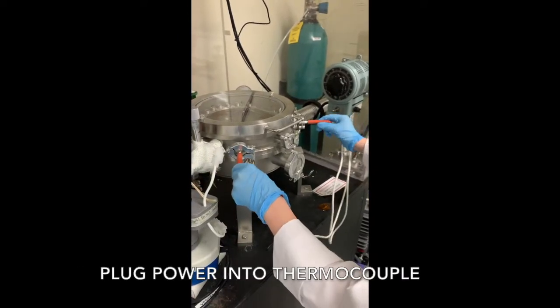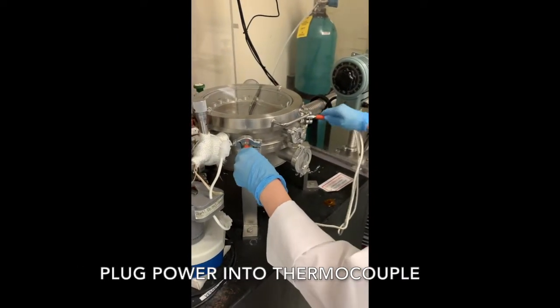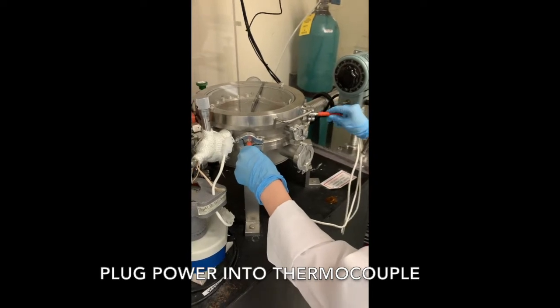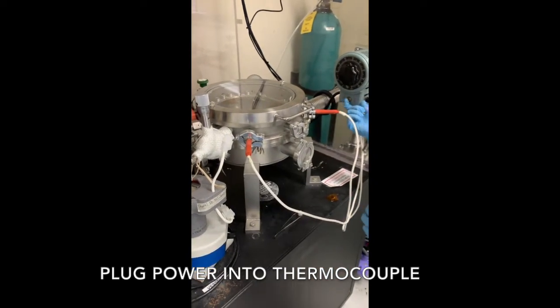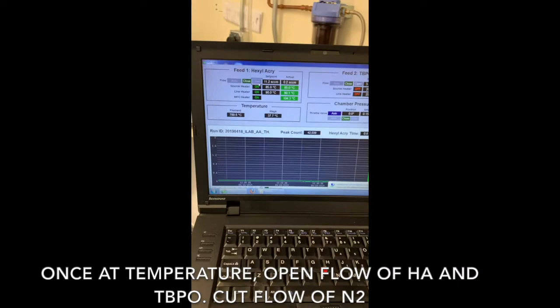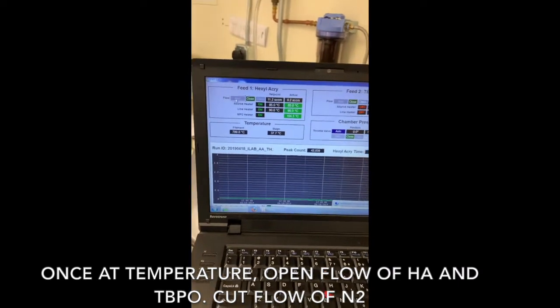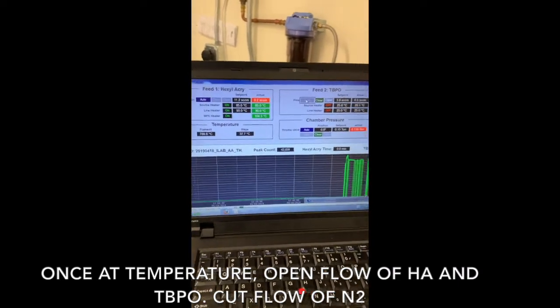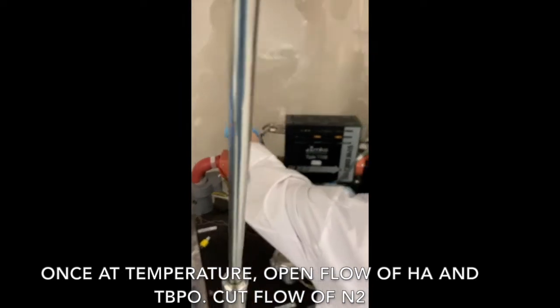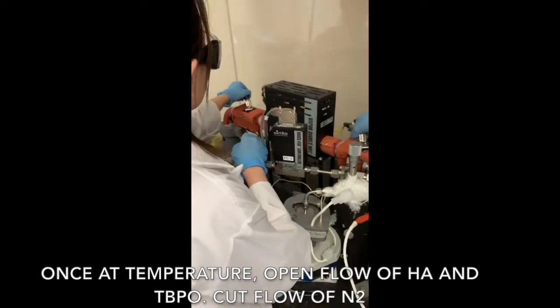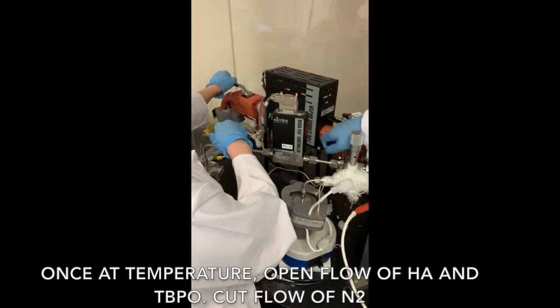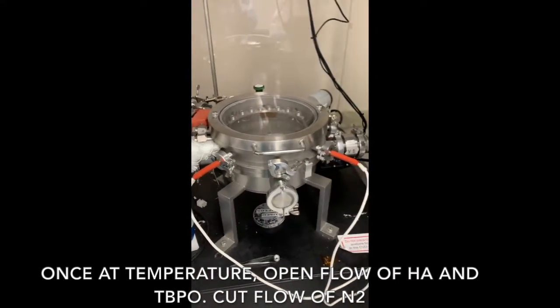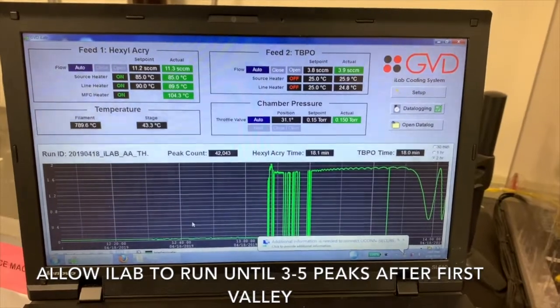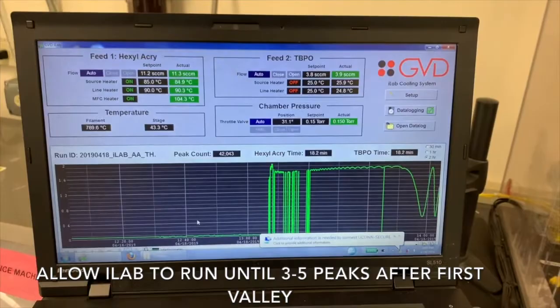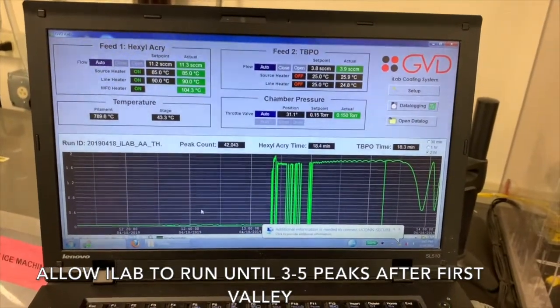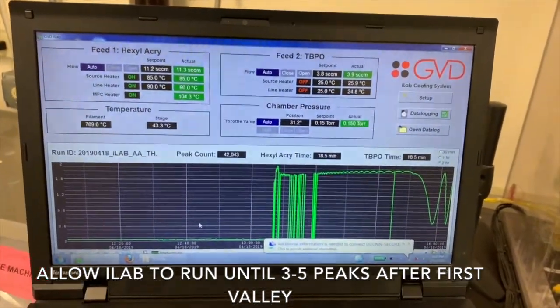Next, the power is plugged into the thermocouple, which will help heat up the stage. Once the temperature is reached, you can then open the flow of hexyl acrylate and tert-butyl peroxide and cut the flow of nitrogen gas. The group then waited and let the experiment run until 3 to 5 peaks after the first valley were seen in iLab.